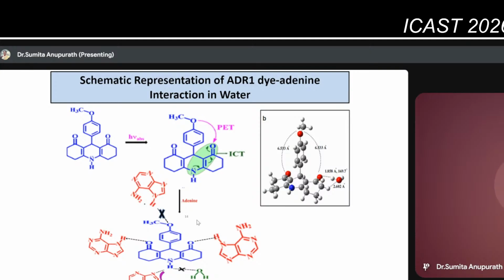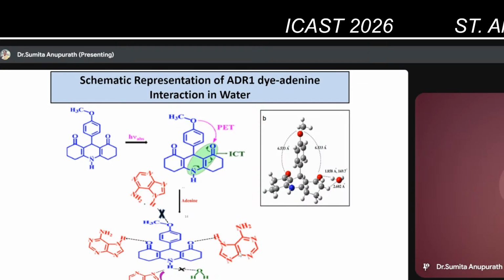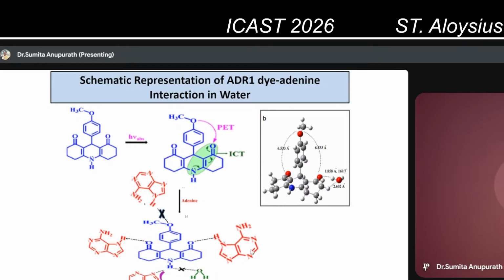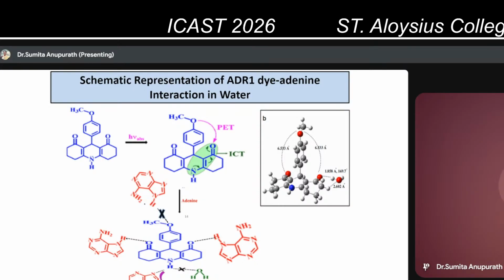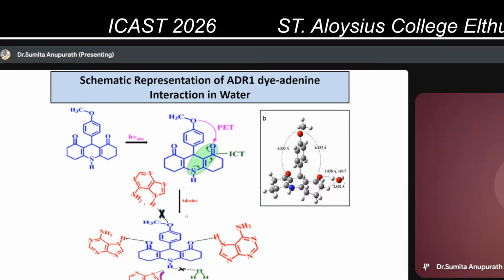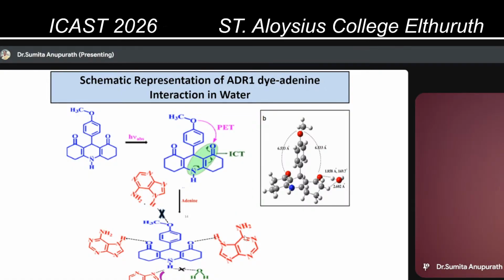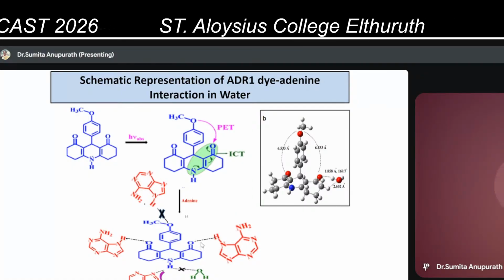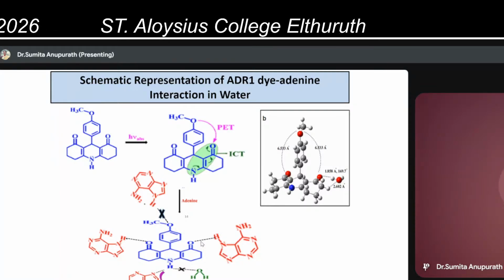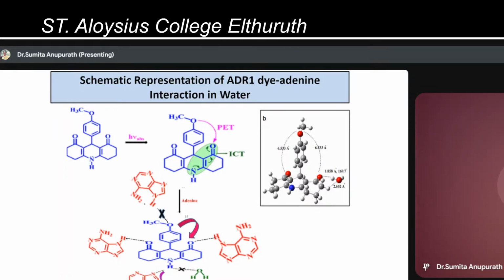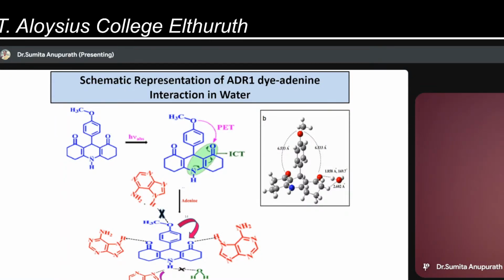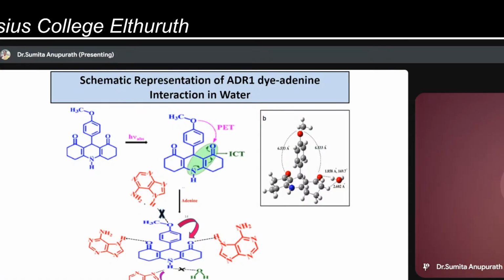should be able to reside between the donor and the acceptor moiety, which does not happen due to geometrical constraints and also due to the stability. So the PET process is not suppressed effectively, which leads to a slight fluorescent enhancement. If it was completely blocked, there would have been a massive fluorescent enhancement, but we have observed only a slight fluorescent enhancement in this case.